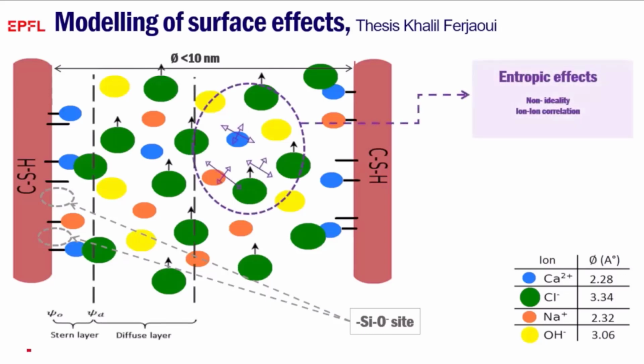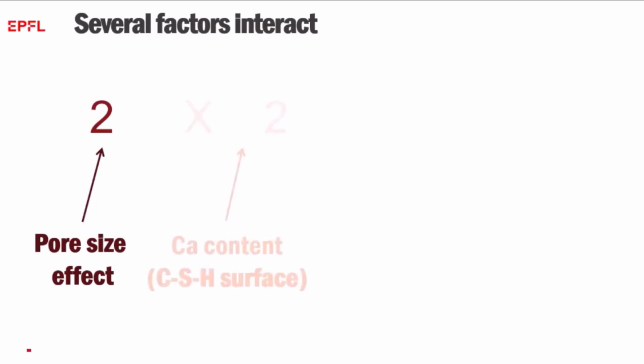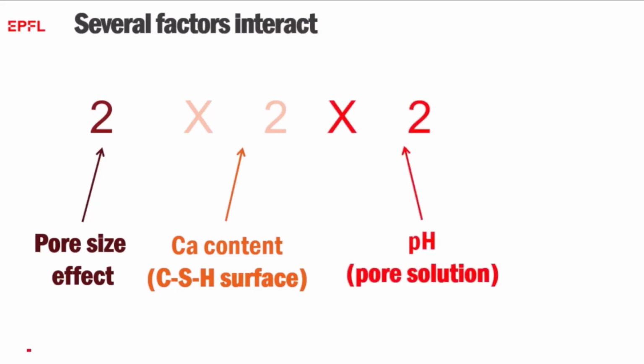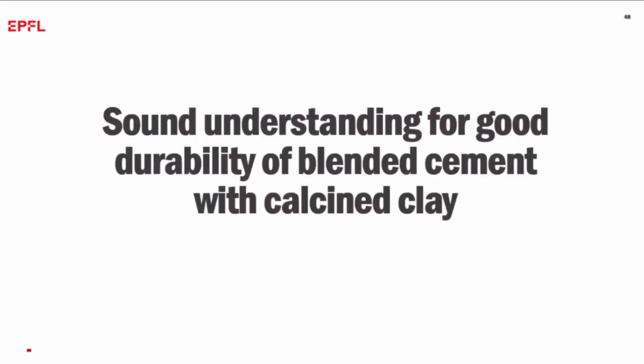We've tried to model this in this recent thesis, and basically we see that there are several factors interacting. So we've got the pore size effect, we've got the fact that the CSH surface changes, and we've got the fact that the pH of the pore solution changes. And so we've got 2 times 2 times 2. I know that equals 8, but our model isn't perfect yet, so that's roughly equal to the 10 times reduction we see in practice. So all of this is really to demonstrate that we have a very sound understanding to be sure that we have good durability of these blended cements with calcined clay.